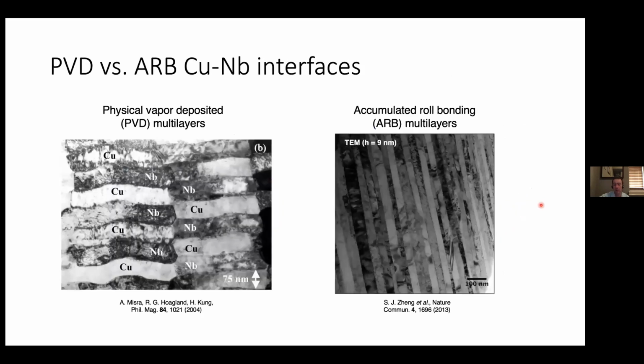Let me give you another example of how you can describe interface properties using dislocation models. For this particular illustration, I will talk about these two types of composites. The composite on the left is a copper-niobium multilayer composite. What you're looking at here is a transmission electron micrograph through a metal laminate with alternating copper, niobium, copper, niobium, copper, niobium layers. Each of them is about 75 nanometers thick, so relatively thin layers. These were made by physical vapor deposition.